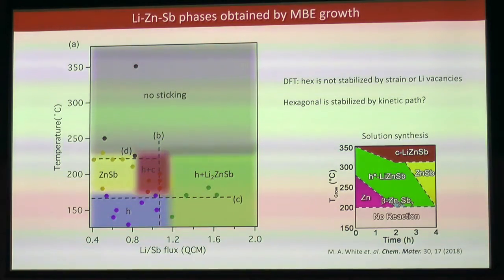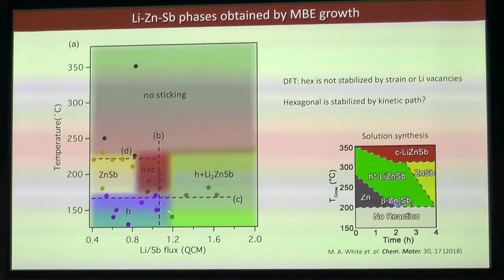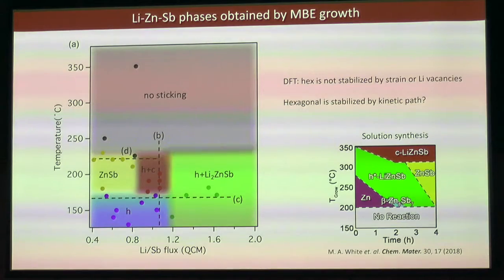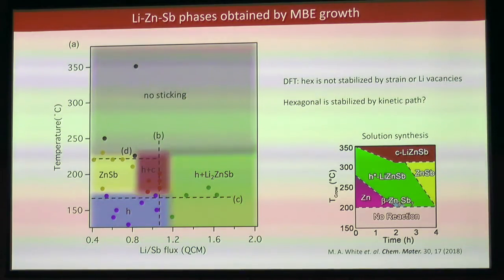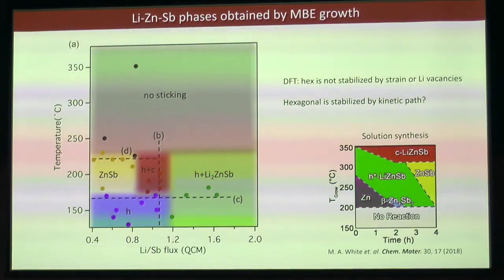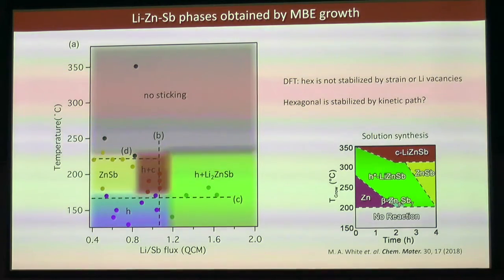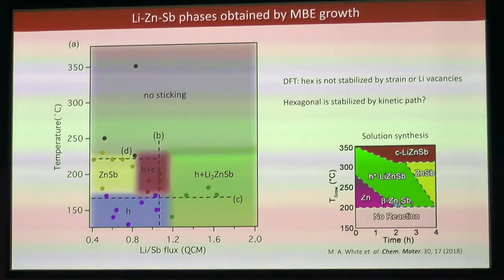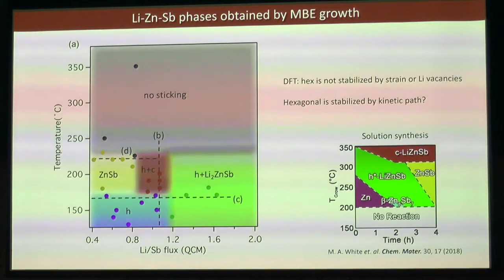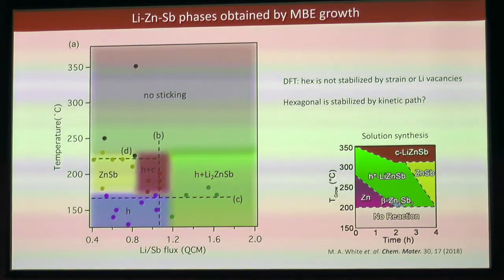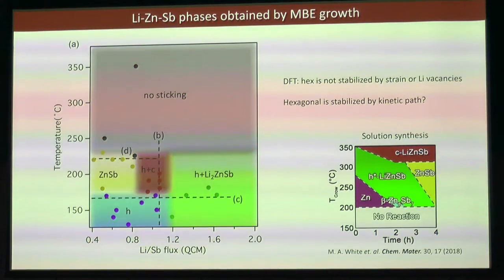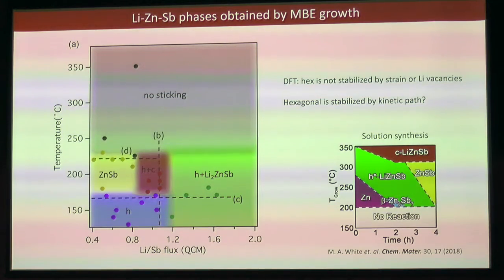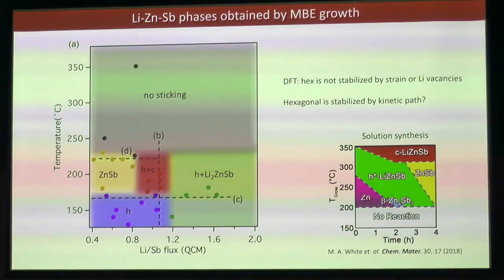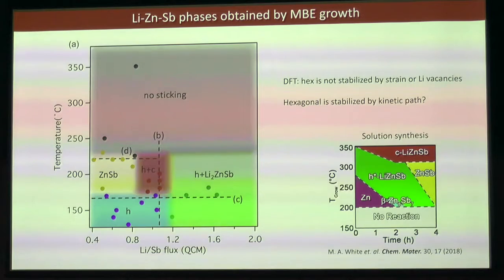You might ask exactly why we've stabilized this hexagonal phase, specifically at lower temperature. It's still not quite clear yet. Some calculations by Karen suggest that no matter what reasonable strain state, the cubic is actually the lower energy phase, but again, only by about 10 meV per atom. And when we changed the lithium composition, that relative stability doesn't change so much. So it really does seem to be driven by kinetics.